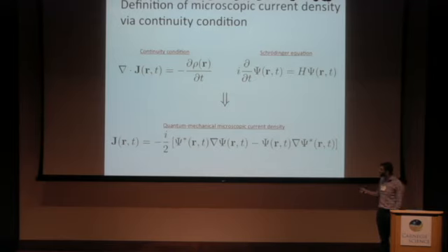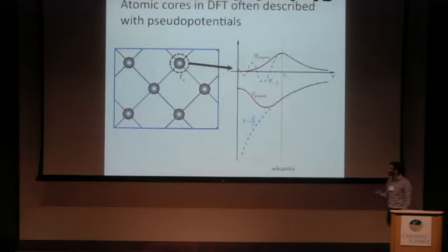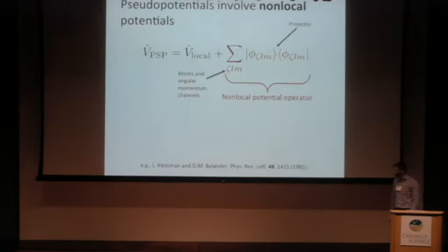However, it turns out that in the context of density functional theory, this current density is problematic for our purposes. And the reason is because of the ways that we describe the core electrons in a density functional theory calculation. To make our calculations computationally tractable, in a cutoff radius, RC, around the atomic nuclei, we treat the wave functions and potential as smoothed versions of the full all-electron wave functions and potentials, so-called pseudopotentials. And for some technical reasons that I won't get into right now, almost all modern pseudopotential implementations involve non-local operators in the potential operator.